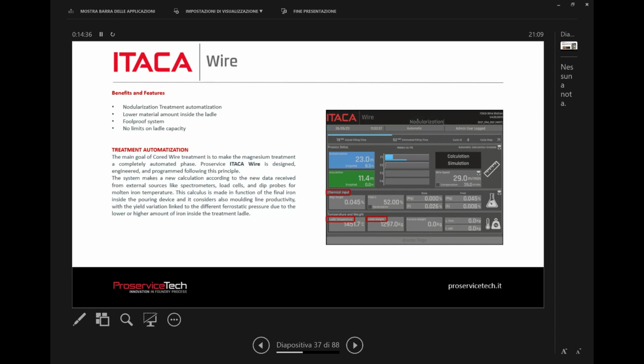What I like a lot about the wire is that from some point of view it is very similar to the Inmold-type converter. In the converter, the logic was fantastic: put the preconditioner inside the ladle, let the preconditioner react, and only after make the treatment. Why? Because you need time to activate correctly the nucleation. With the wire, every addition you make in the ladle works very well. Every addition, because you create basically a new corrective phase compared to the sandwich or tundish process.